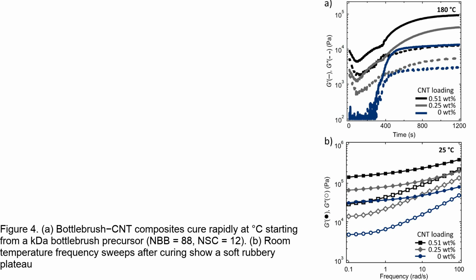Bottlebrush CNT composites cure rapidly at 180 degrees Celsius starting from a 150 kDa Bottlebrush precursor, NBB equals 88, NSC equals 12. Room temperature frequency sweeps after curing show a soft rubbery plateau. In this figure, the curing behavior of Bottlebrush CNT composites is shown. The composites cure rapidly at 180 degrees Celsius, as evidenced by the increase in storage, G', and loss, G'', moduli. Room temperature frequency sweeps after curing show a soft rubbery plateau.